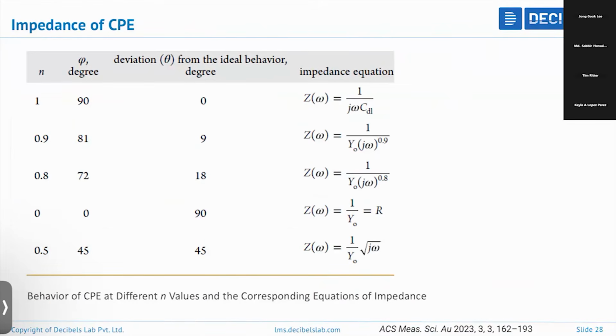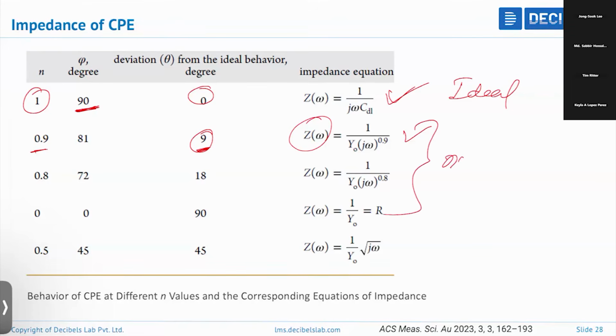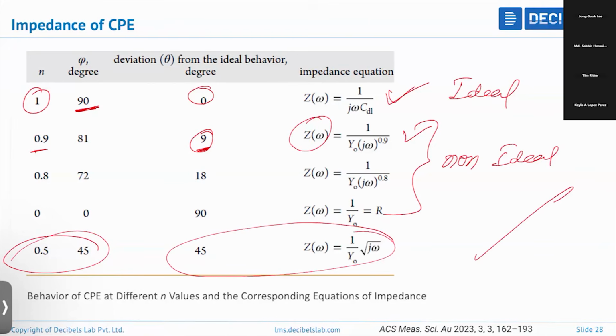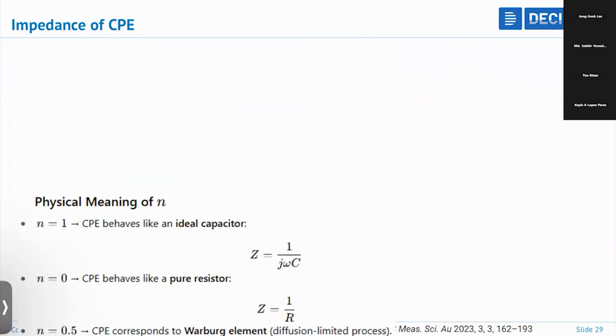Now, if n is equal to 1, this is the ideal capacitor, and it is exactly parallel to the y-axis. If n is equal to 0.9, it is tilted by 9 degrees. So the equation corresponding to that is impedance equal to 1 by Y0 into (j omega) to the power of 0.9. So these are all non-ideal. That is called constant phase element. If the line is coming at 45 degrees, this corresponds to the Warburg diffusion, the last component that I'll be discussing.